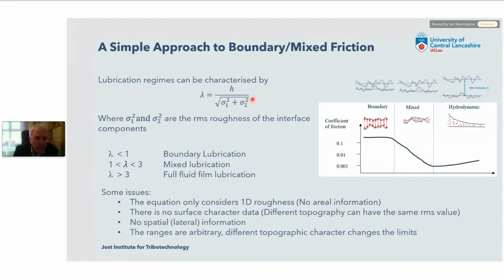Most of you will recognize this. This is the lambda ratio, and we can characterize the various regimes of lubrication, boundary, mixed, and hydrodynamic, by taking the ratio of the film thickness and the square root of the sum of the squares of the RMS roughnesses, or Rq roughnesses if you like, adding them together and taking the square root. By looking at the ranges of the resulting parameter lambda, we can determine which regime of lubrication we're in: boundary, mixed, or full fluid film, as we work our way through the Stribeck curve. Very commonly on the bottom, we've got duty parameters, which involve viscosity, load, and speed. However, we can replace this axis with the lambda value. So as the lambda ratio increases along the x-axis from 0 to, let's say, 3, we can move through the various regimes.